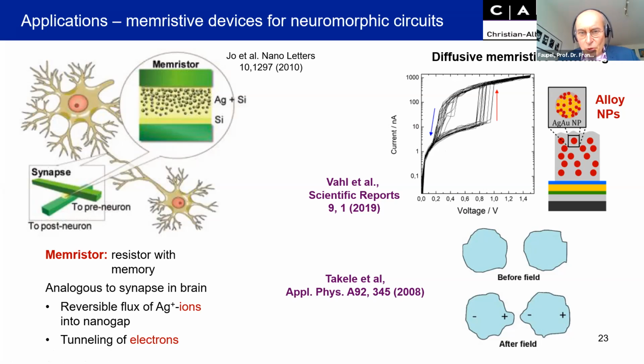And then if you go back with the electrical field, at a second threshold, they should switch back. And this is something which we were recently investigating in more detail based on very old work of our group. Already in 2008, we noticed that in our nanocomposites, we form such channels of highly conductive regions because of the huge electrical field between the particles. Ions are released, for instance, from silver particles, and they nucleate on the opposite side, and this leads to the formation of conducting channels. They can also be dissolved again by Joule heating or driven by the high surface energy of the channels. And based on such approaches, well, at that time we had no idea about memristive devices. This came later. But using now alloy particles, where we can tailor the amount of ions that can be released, we can tailor the behavior of such memristive switching devices.